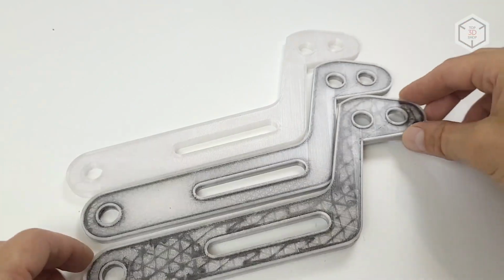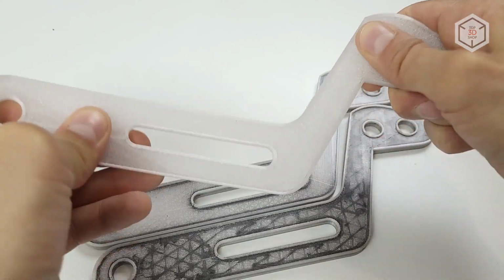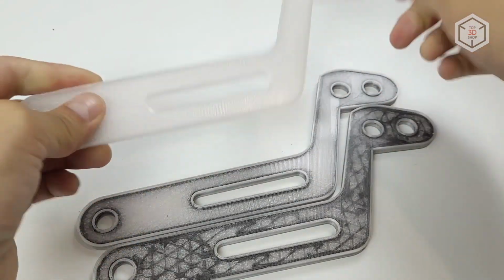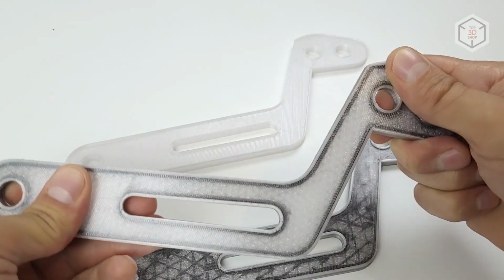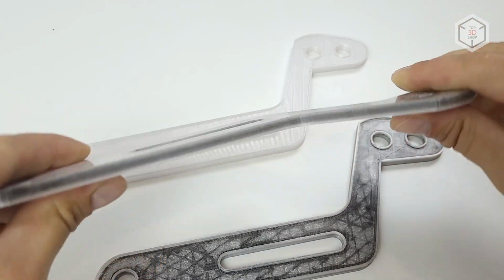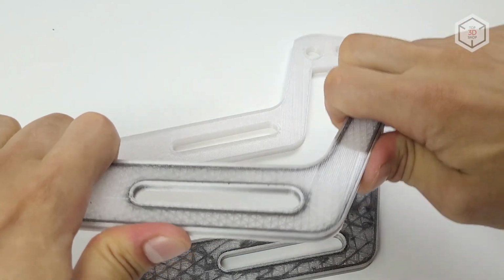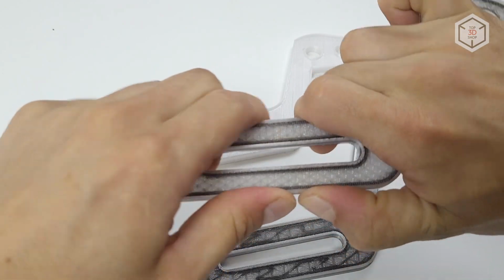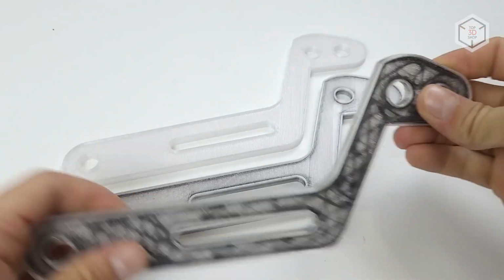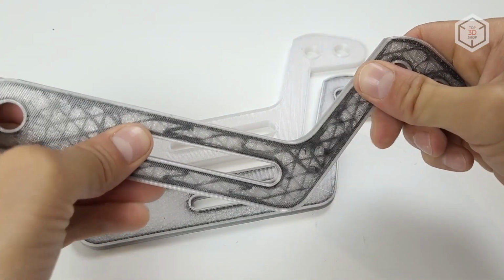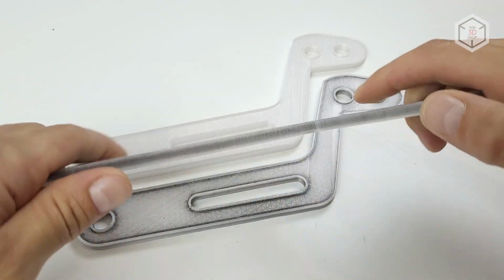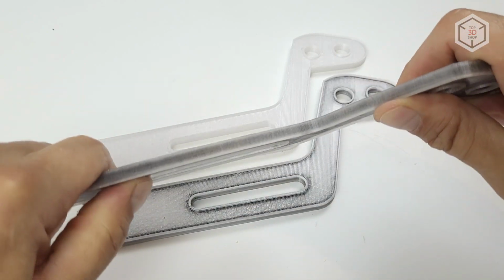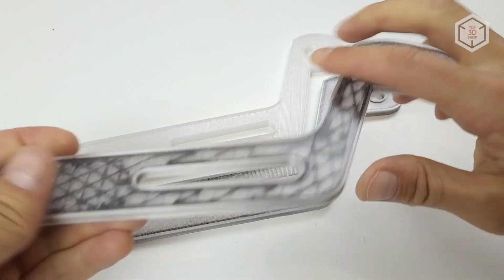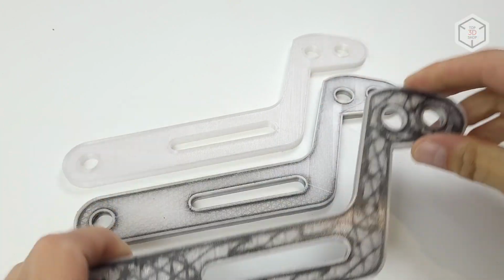As expected, the plastic part turned out to be the softest and the most unstable. The sample with reinforced contours felt much stronger, not only along the fibers, but also across. Apparently, the fiber fused into the plastic gives the reinforcement effect and strengthens the part in all directions. And the part with the fiber added wherever possible felt the most rigid. The quality of the printed part is very good, although the same difficulties as in the first test also occurred. They were especially evident on the fully reinforced part.